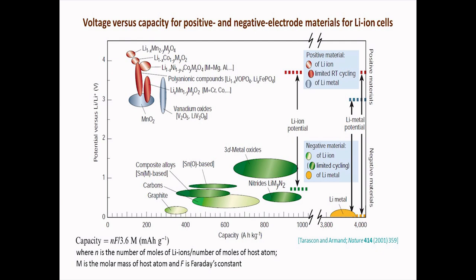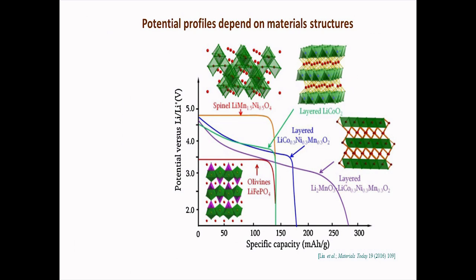However, there is another important aspect, which is how stable these materials are upon repeated lithiation, delithiation. That is the cycle life of the material. Anyway, looking at the fundamental aspects of the voltage profile, these are all cathode materials where lithium will form a predominantly ionic bond with the oxygen lattice. However, one sees not only are the voltages different between different materials, but even if something starts at the same voltage, the voltage profile is very different. Sometimes it is very flat, sometimes it is slopey.